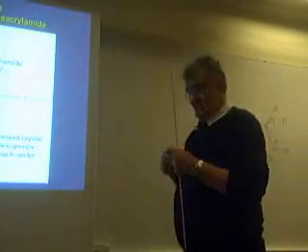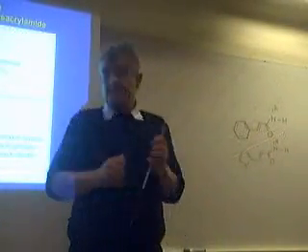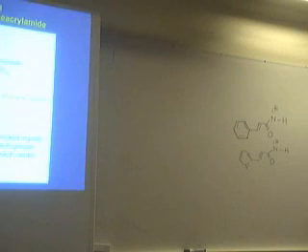And growing in the presence of thienylacrylamide, because thiophene and benzene are very similar structures. Okay? And what happened is that sulfur is a heavy atom. We have also labeled one of the molecules with deuterium. We sectored the crystal. We went to Brookhaven. We measured the crystal structure of each one of these sectors at liquid helium temperature, and we found that the space group of each particular sector is different.